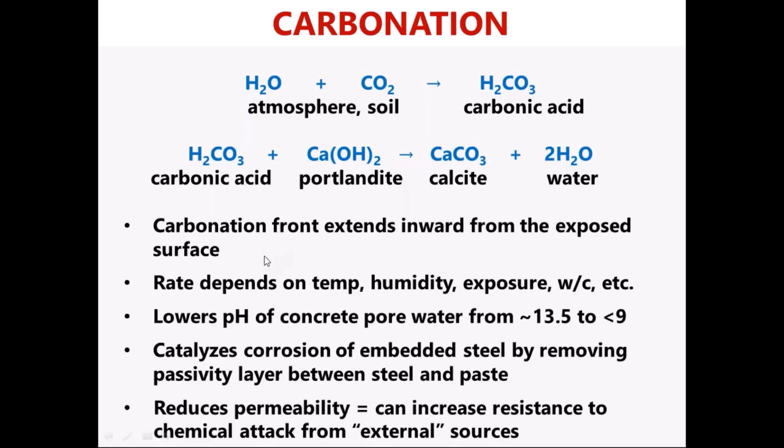Generally speaking, the older the concrete, the deeper the carbonation horizon will be. The effect of carbonation is that it lowers the pH of the concrete paste from 13 or 14 to less than 9, and that reduces the permeability of the paste, which means it's less susceptible to externally applied chemicals getting in and ruining the concrete.